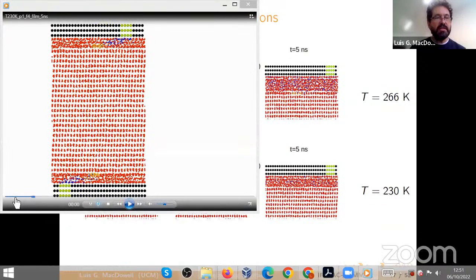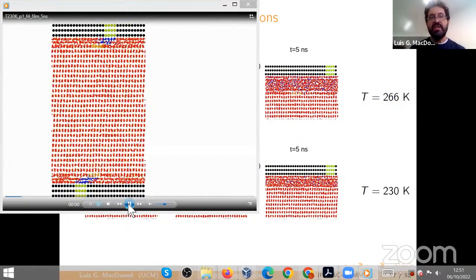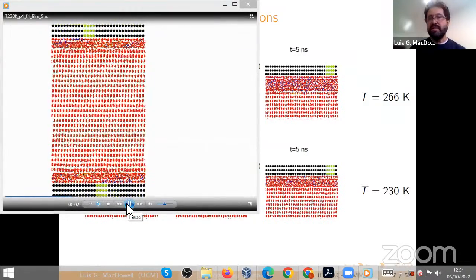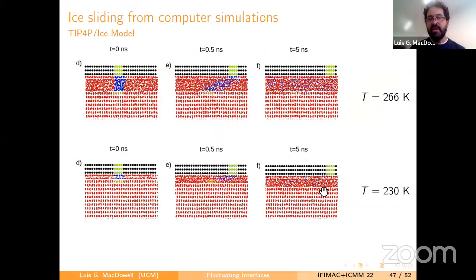Okay, did you see that? So it was just 2 layers thin, very thin, but in just a few nanoseconds, it's becoming thick enough. And so if you look here, in 5 nanoseconds, you are at much lower temperature, but the film thickness is just as large.